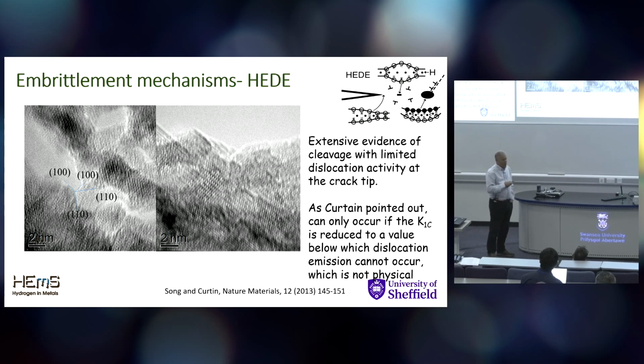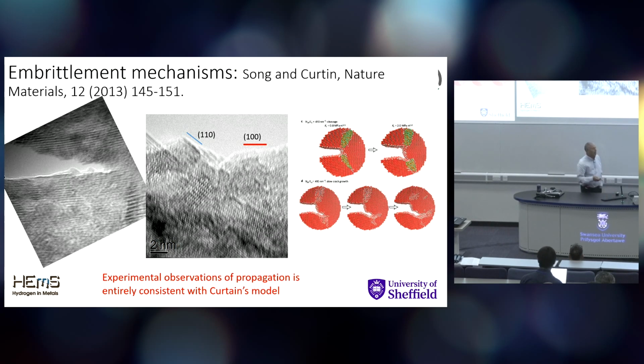it's physically impossible for the HEDE mechanism to actually take place because, as he points out, the K1C has got to be reduced to a value well below the dislocation emission, which is not physical in itself. So he suggests that that mechanism, as written down, is not correct. I won't go through his mechanism of propagation, but you can read his paper. It's based on atomistic modelling, and I think it quite neatly shows crack propagation behaviour.